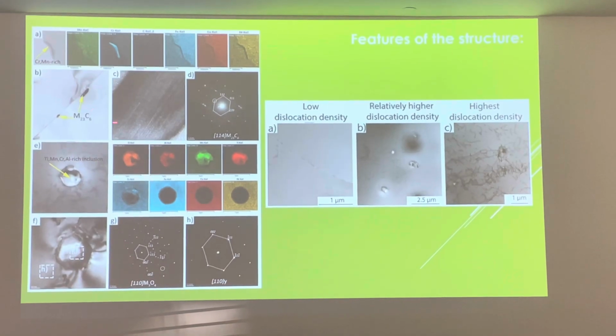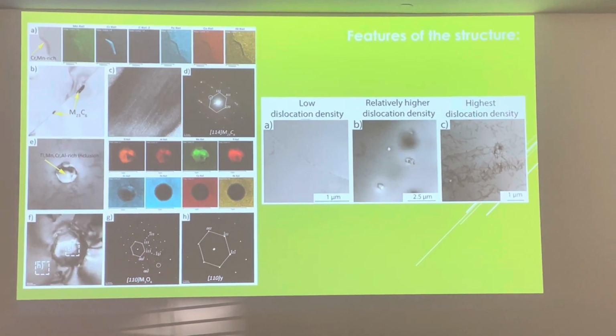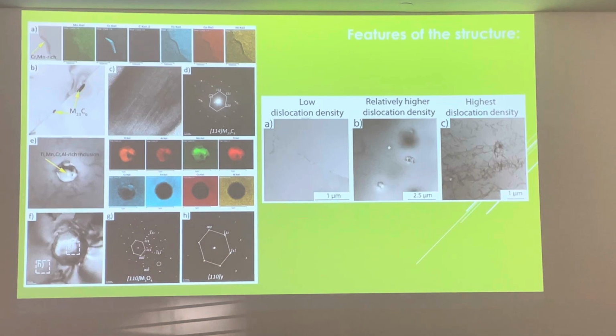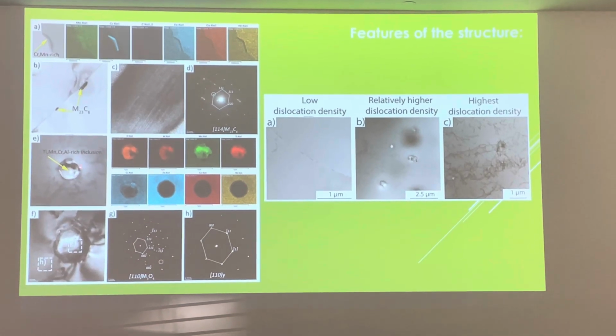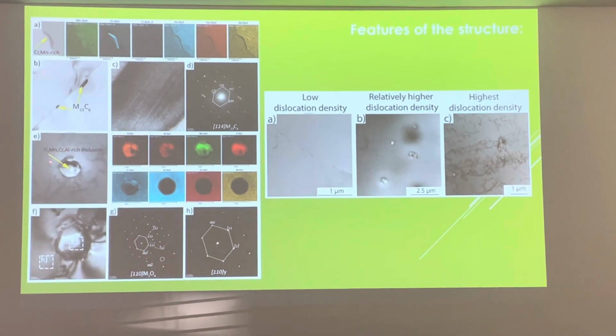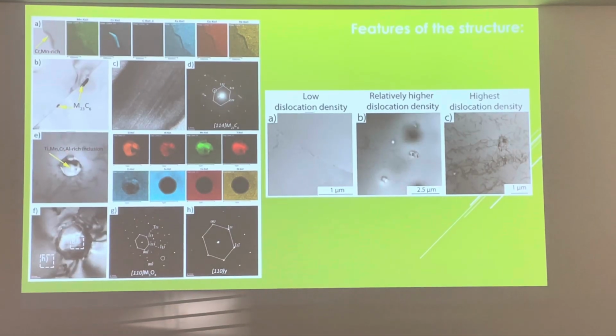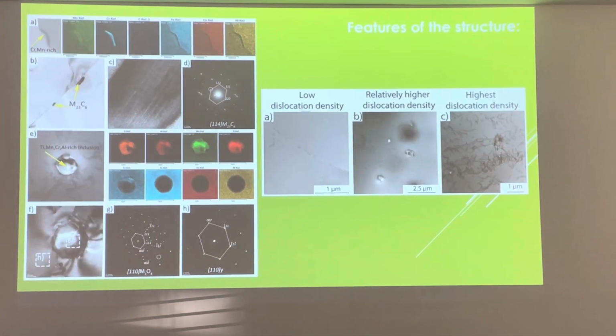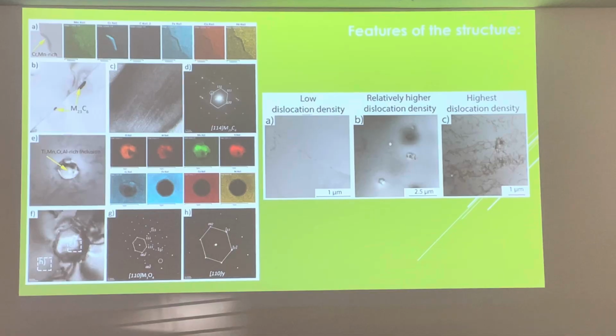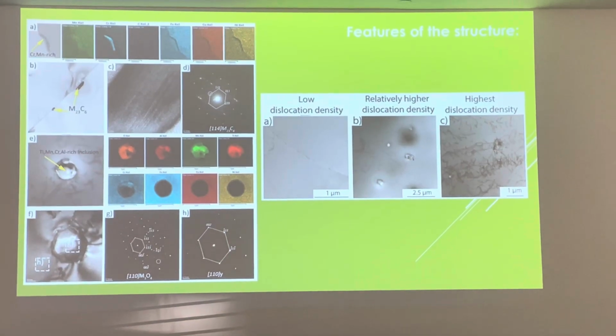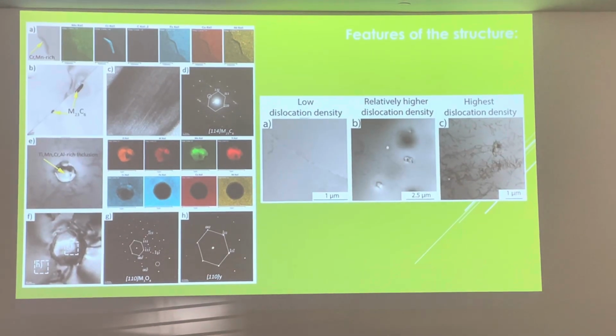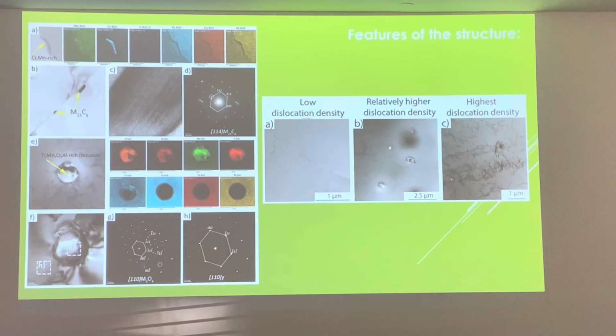Also, we have observed artificial elements, let's say. These are complex titanium, manganese, chrome, aluminum inclusions with spherical shape. This is connected with the purity of the powders and the solidification process.